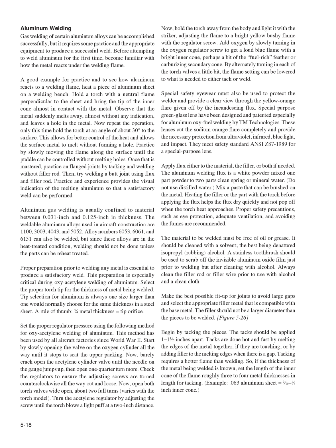The material to be welded must be free of oil or grease. It should be cleaned with a solvent, the best being denatured isopropyl rubbing alcohol. A stainless toothbrush should be used to scrub off the invisible aluminum oxide film just prior to welding but after cleaning with alcohol. Always clean the filler rod or filler wire prior to use with alcohol on a clean cloth.